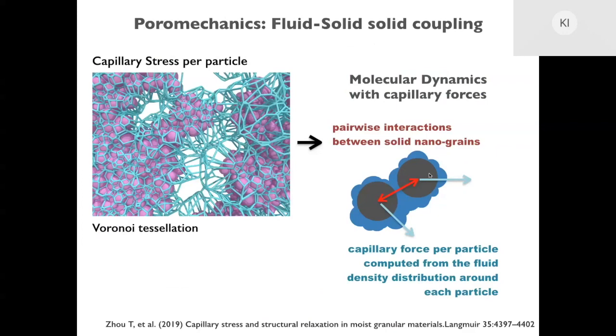So basically now, usually we were doing simulations with only pairwise interactions between the cement grains. This will keep the grains together. This is because of the nature of CSH. They're sticking together. But now we can add extra forces, the capillary force that each particle has due to the water distribution around it, and this will show us how the material is relaxing due to the distribution of water